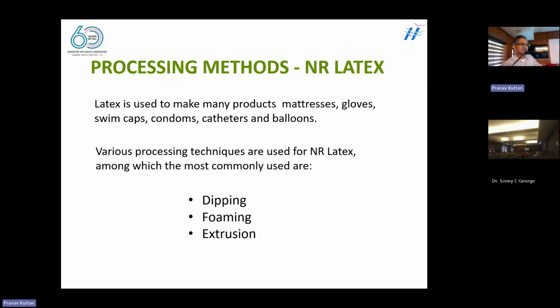So the products which we see, the KSRTC seats which you are sitting on, or the beds you are lying on, or the rubber bands you are using, these are all subjected to different processes of converting this latex into that product. One of the processes is called dipping. It's a simple process, dipping of a mold into the latex, which will form the shape of that mold, and which is then dried in an oven for some time for the process of vulcanization, and then you can use it after taking it from that. The simplest example is the gloves. A glove mold made of porcelain or glass, you can put it into the latex. When taken out, it forms a layer of latex over the mold. Then you can dry it in the oven at a specific temperature for a specific time, which can be predetermined.